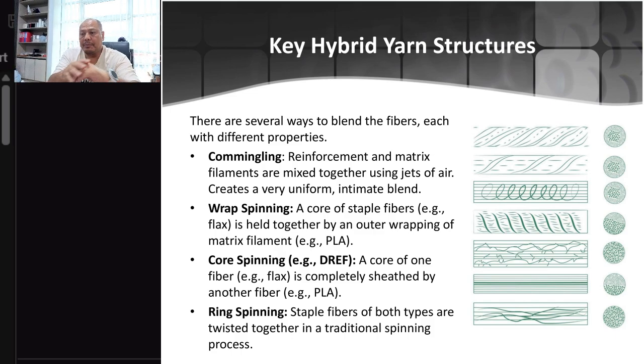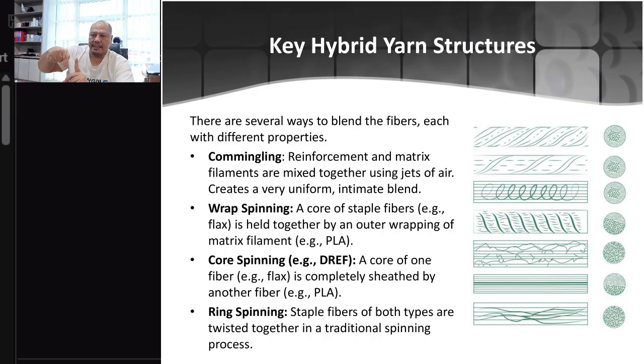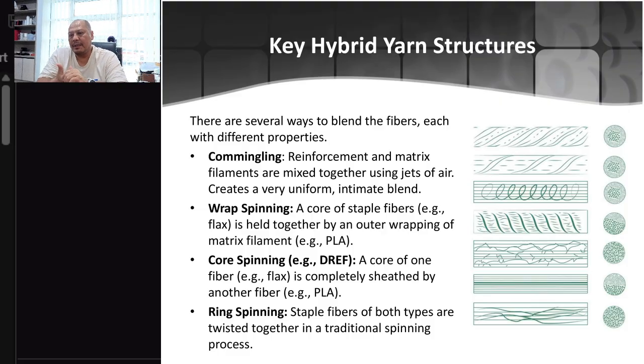The second is wrap spinning. The core of staple fiber, like flax, is held together by an outer wrapping of matrix filament like PLA. You can see in the second picture how the core staple fiber is held together with the outer wrapping of matrix filament. Then core spinning: one yarn becomes a core, like flax or whatever fiber, completely covered by another fiber like PLA. Then ring spinning: the other is staple fiber. Both types are twisted together in the traditional spinning process, so they are mixed and blended in the following system.